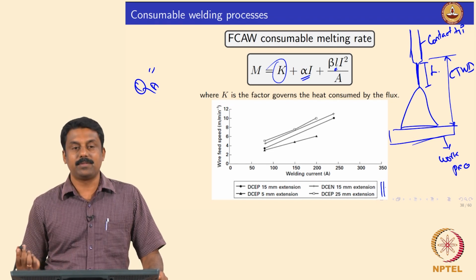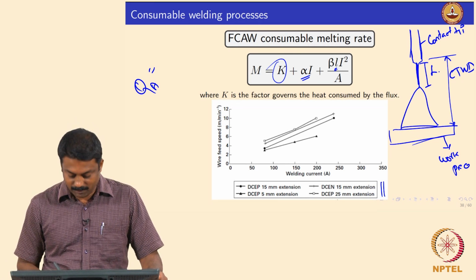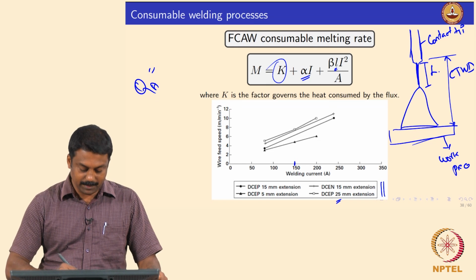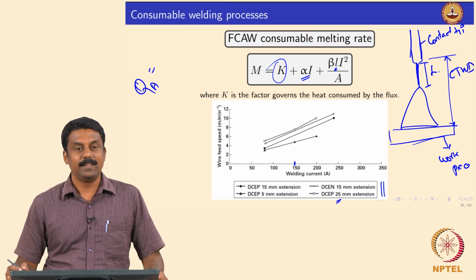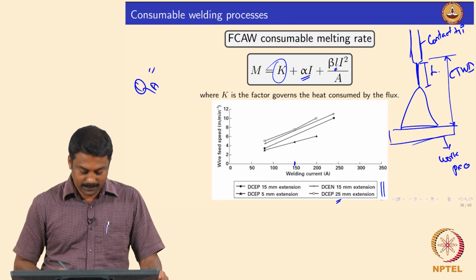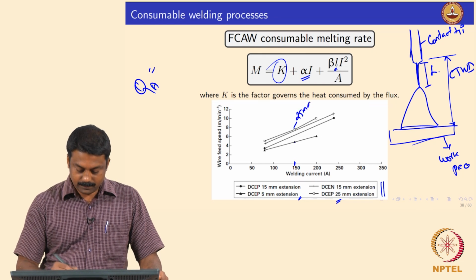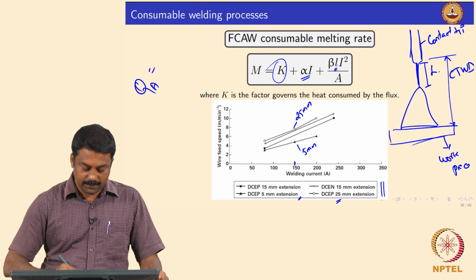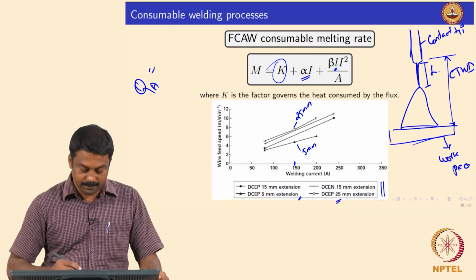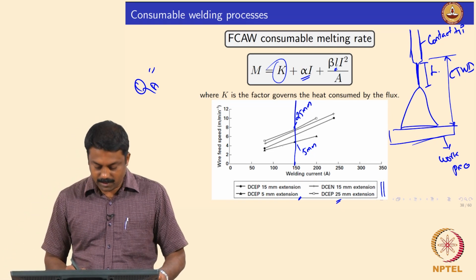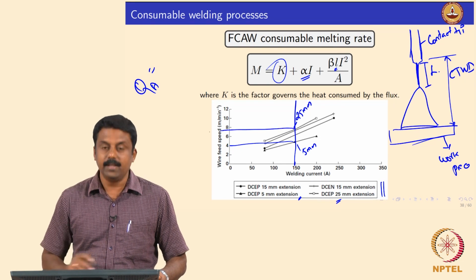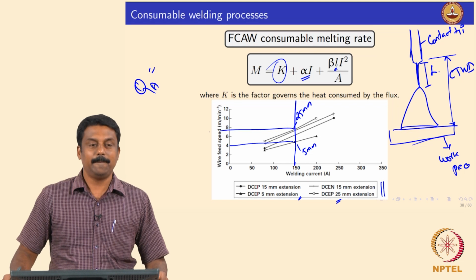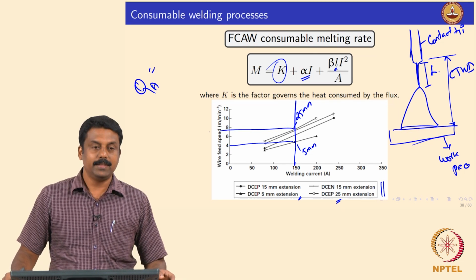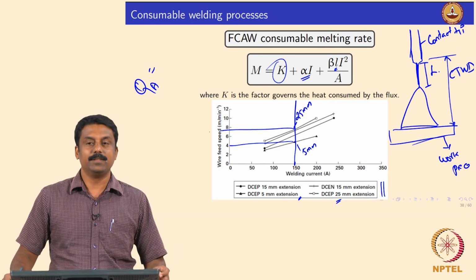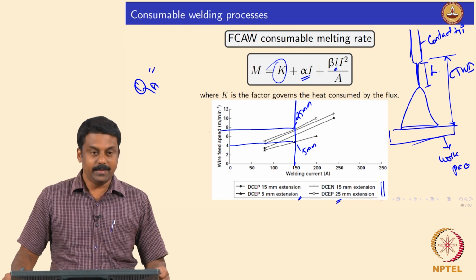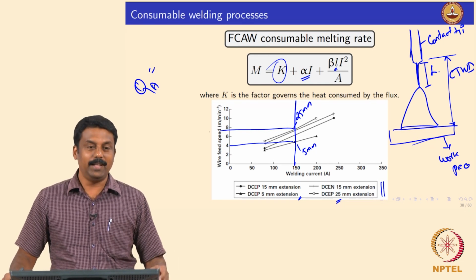So, if you increase stick out length, what happens to melting rate? If you increase stick out length, for example to 25 mm for a given current of 150 amperes, stick out length increases means melting rate also increases, isn't it? So, this is the low stick out length 5 mm and this is 25 mm, isn't it? So, at 150 amperes you are welding with a 2.4 mm flux cored arc welding wire. Just by changing stick out length, you can almost double the melting rate, okay, from 4 m/min to 8 m/min, it is almost doubled, isn't it? But current is the same. So, why is the melting rate changing?